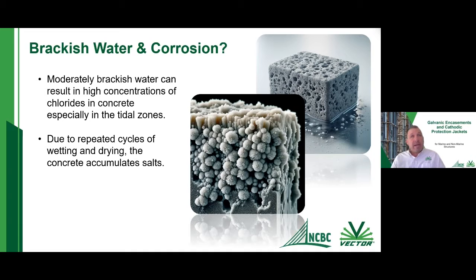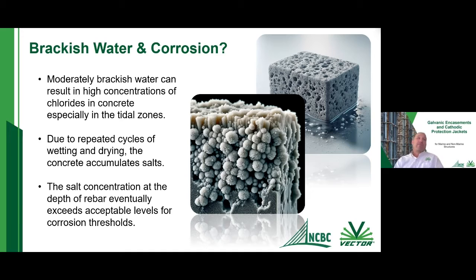So when it dries again and then re-wets, you can actually have very, very high elevated levels of chlorides in your concrete, even in brackish water where you don't have very high salt concentrations. Some of you may have come across this, where you're out in a brackish water area where there's not a lot of chlorides in the water, but you can still see significant corrosion, especially on reinforced concrete structures, due to the concrete absorbing that water over and over.